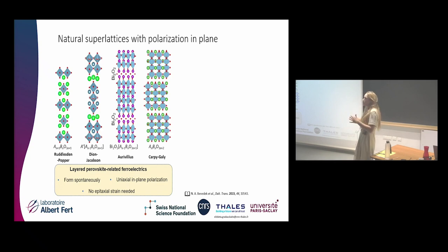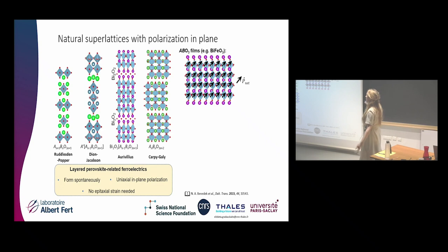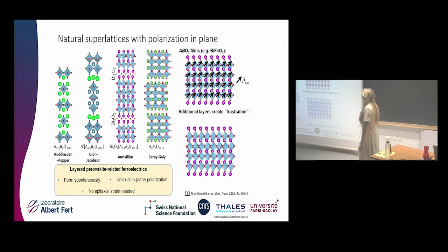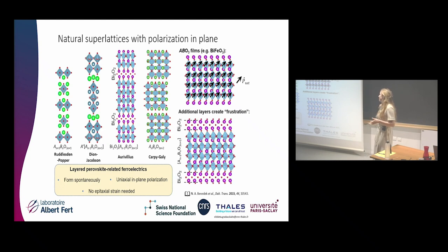But essentially, these materials just form spontaneously, and they all have one thing in common, that they tend to have uniaxial in-plane polarization. So in this case it would be in the base of the unit cell as you see it now. And the reason why they have in-plane polarization, unlike normal ferroelectrics, like for example BFO, where you would have out-of-plane polarization along one of the diagonals, is that these additional layers electrostatically create frustration. So we squeeze in our perovskites in between something that's charged.